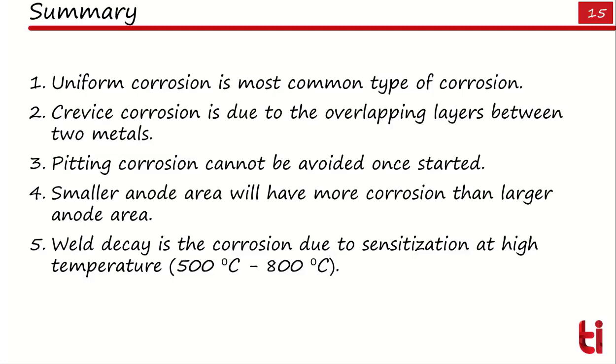Weld decay is the corrosion due to sensitization at high temperature in the temperature window of 500 to 800 degree centigrade. If you cannot avoid the weld joints in your design, you should either give the heat treatment at higher temperature, or you can use steels which contain either niobium or titanium to avoid weld decay in your design.